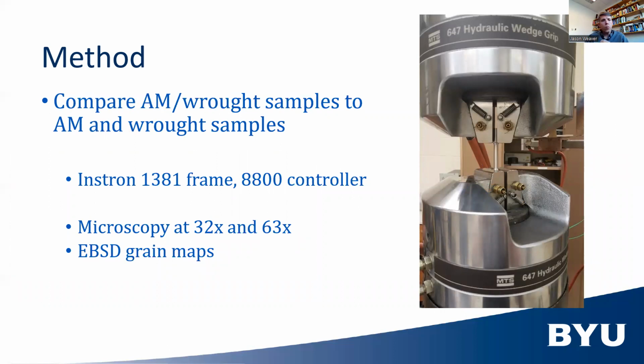Here's some of the equipment that we used. We did our torsion and tensile testing in an Instron 1381 machine. We did microscopy observations at 32 and 63 magnification, and then we did some EBSD grain maps.